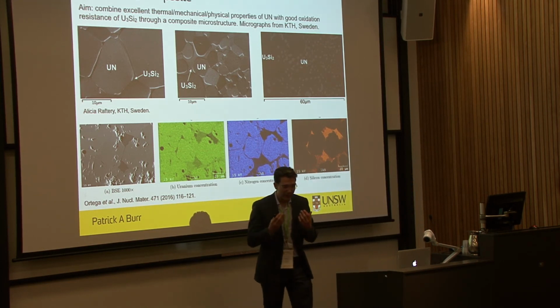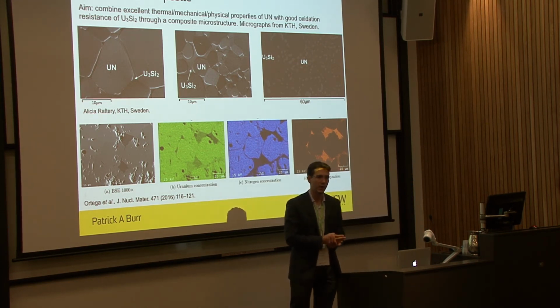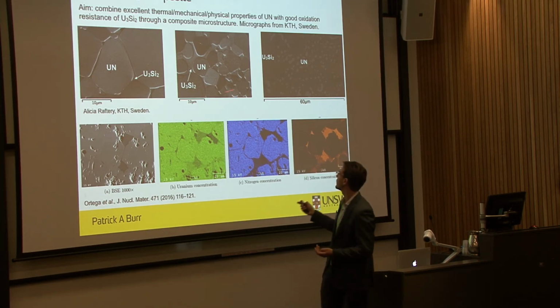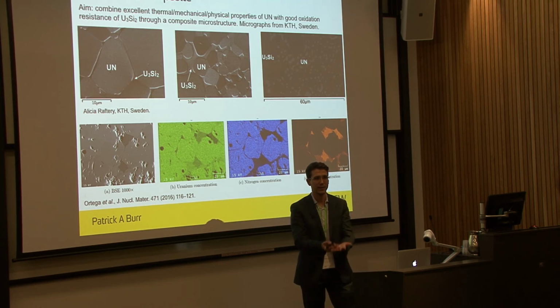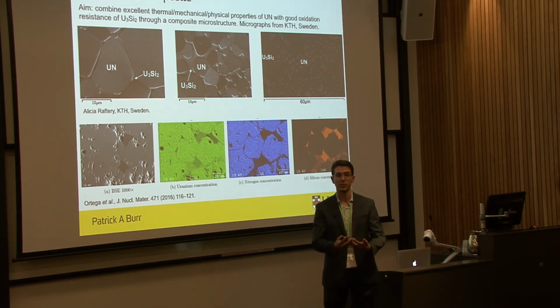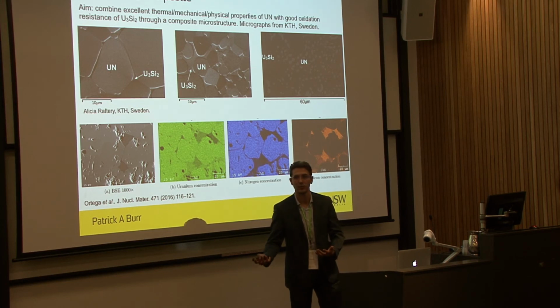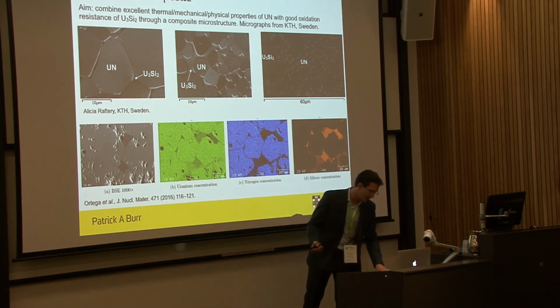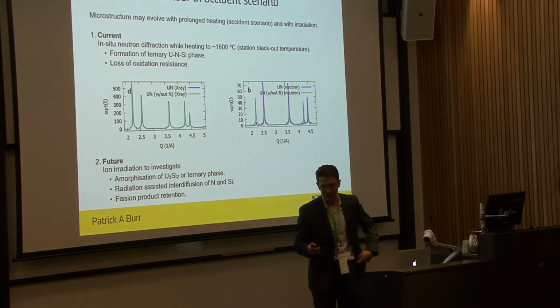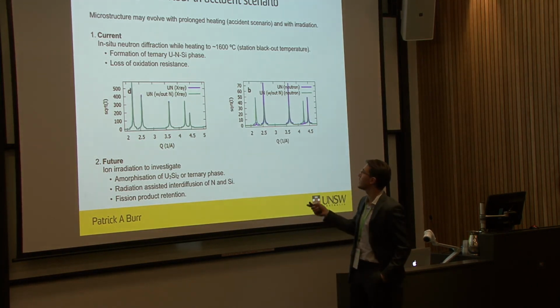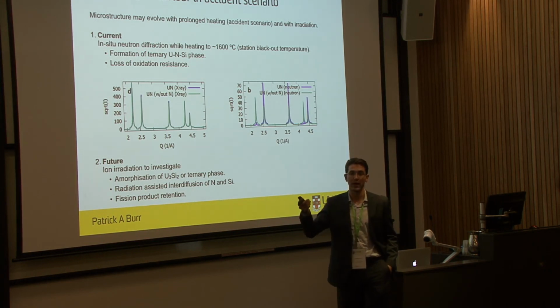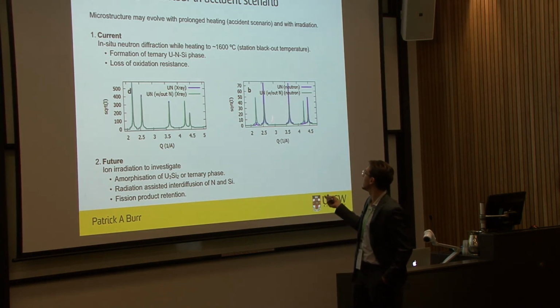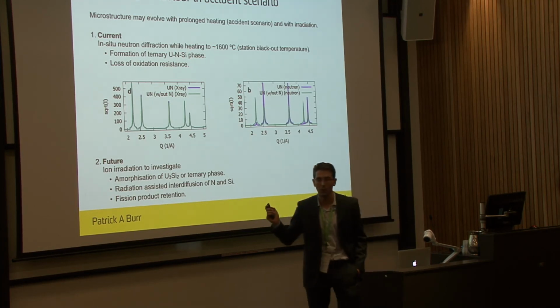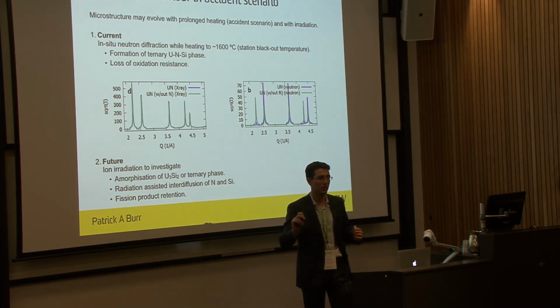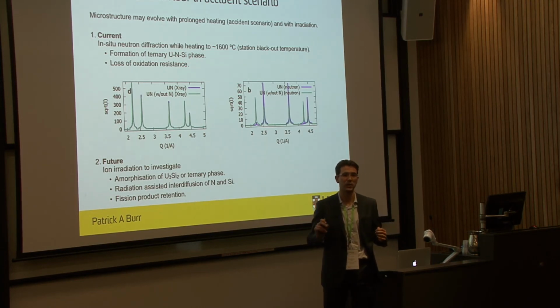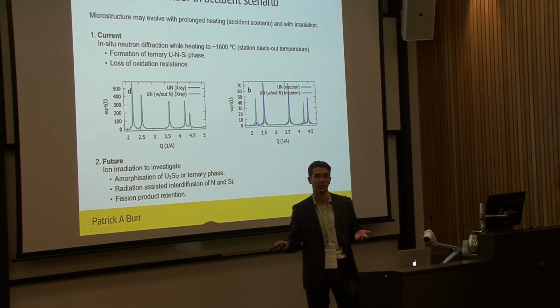Now, if the material properties are so good because of the microstructure, then the obvious question is, yes, we can make this lovely microstructure, but when you put it in an accident scenario, do you retain it, or do you change the microstructure and therefore get something that oxidizes very badly? That's what we're doing right now. This is a project led by Edward O'Bard, on the floor actually. We're working with KTH, ANSTO, and Westinghouse to do in situ heating of this composite material while we do neutron diffraction to see if at high temperatures you do start forming ternary phases or not.